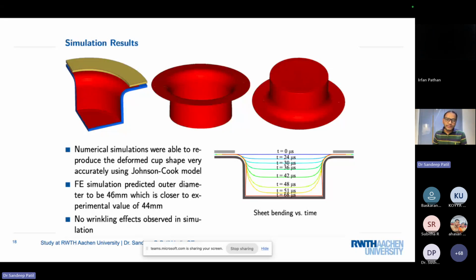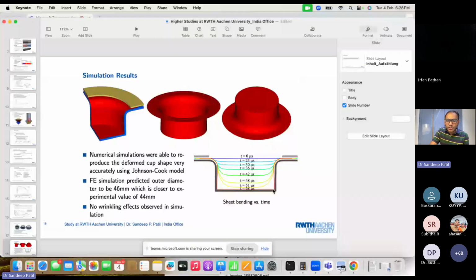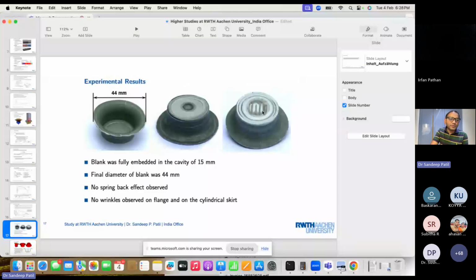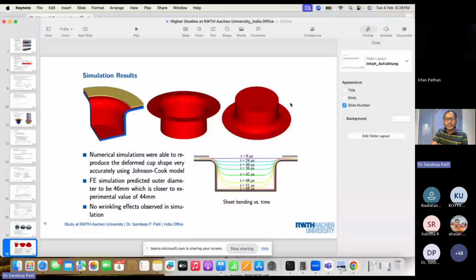There were no wrinkles observed, and as we see with respect to time, it was going nicely into the die, and at the end you can see it going very sharply into the corners and making exactly the shape we observe experimentally. So if you see here, exactly the sharp corners we observe here in the simulation. So that was very interesting for us.